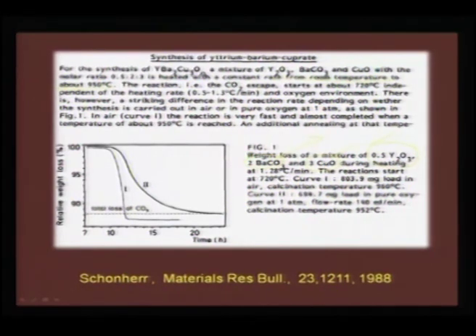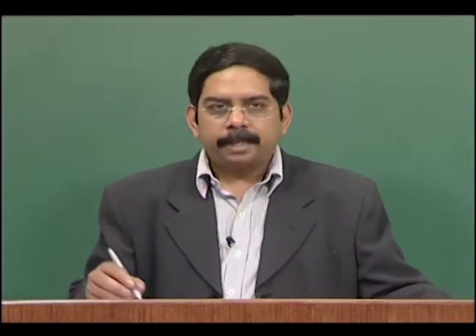So, once the carbon dioxide escapes, you would see there is a weight loss of around 13%, and then the final compound is formed here. The final compound corresponds to YBCO. But the problem here is, if barium oxide were also stable, then it would be easy to take all the component oxides into the picture and make the phase much more easily. But barium oxide is very reactive, therefore it always ends up as barium carbonate, and barium carbonate undergoes decomposition only